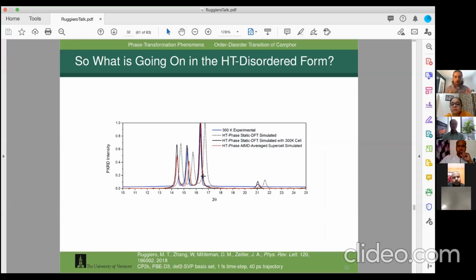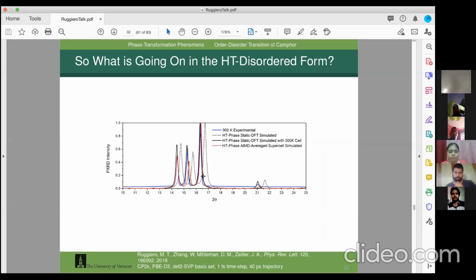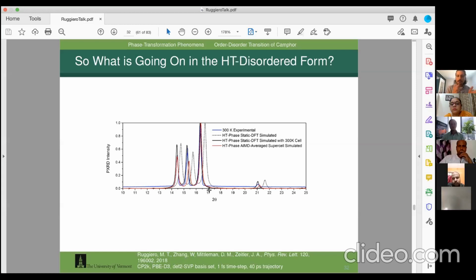So we're almost there, but the most accurate method was actually taking all the positions from the molecular dynamics simulation and averaging them, then generating a powder X-ray pattern. That's the red line, which agrees quite nicely with the experiment. So as we got more physical in our computational model, we got better agreement with experiment.